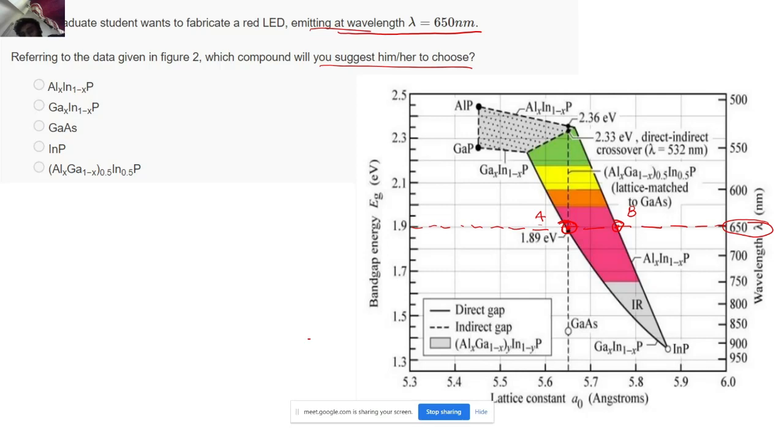Okay, I will help you. For point B, we are moving between indium phosphide and aluminum phosphide. We are moving along this trajectory, and we have a mole fraction here. By changing the value of this mole fraction, we can move from the start of this InP, and go like this. The material is still direct band gap, and the moment you reach here, your material becomes indirect band gap, because it is written here, direct band gap and indirect band gap. And then we move towards the aluminum phosphide here.